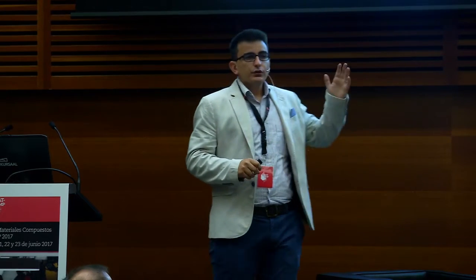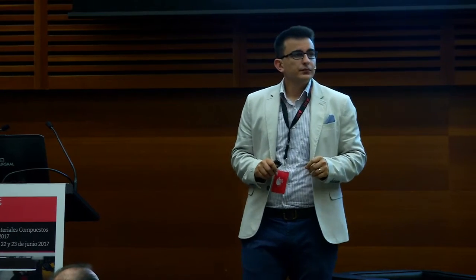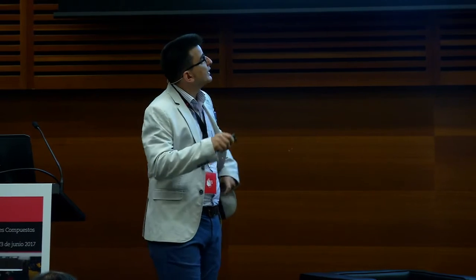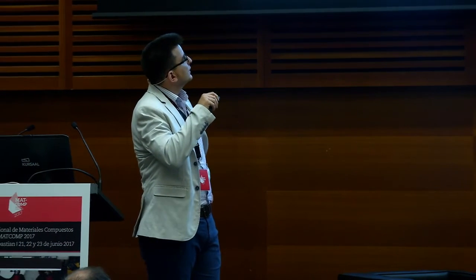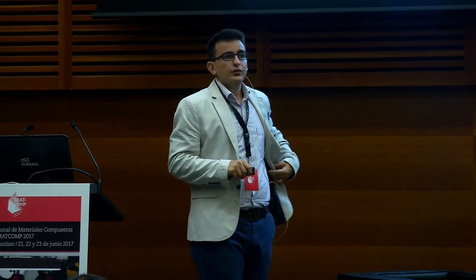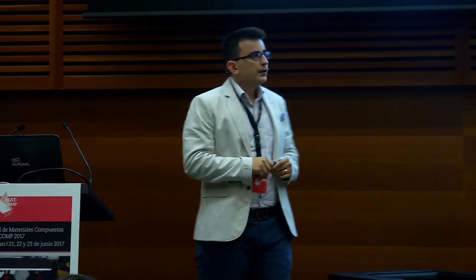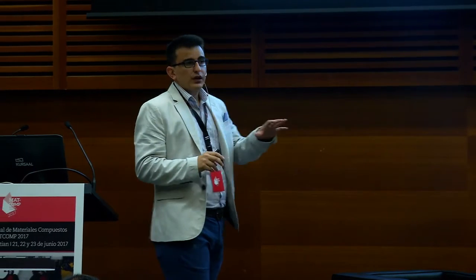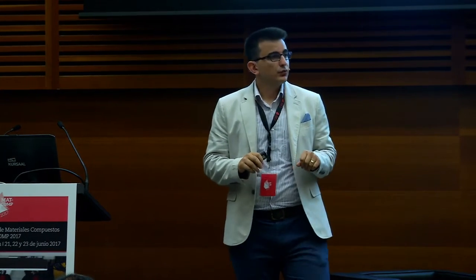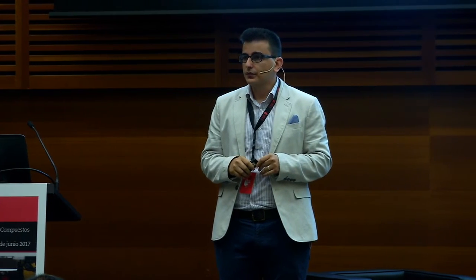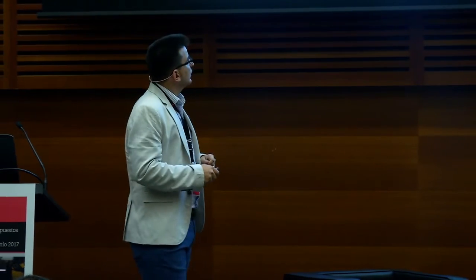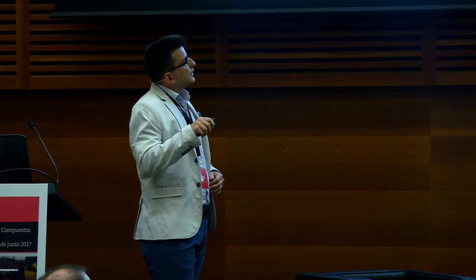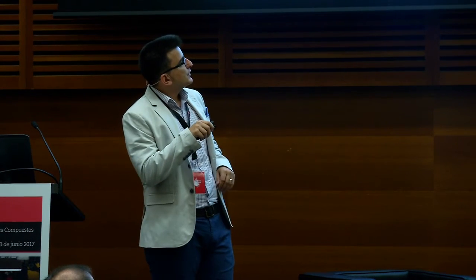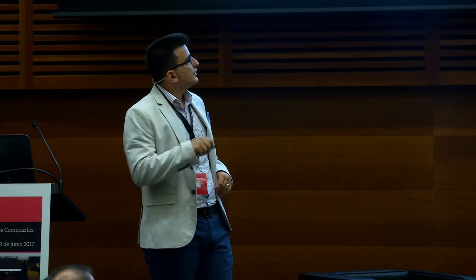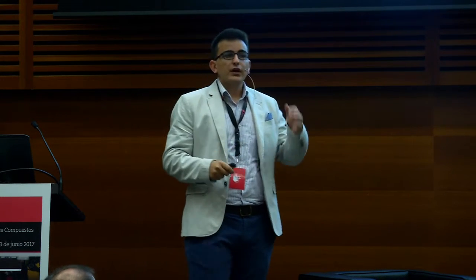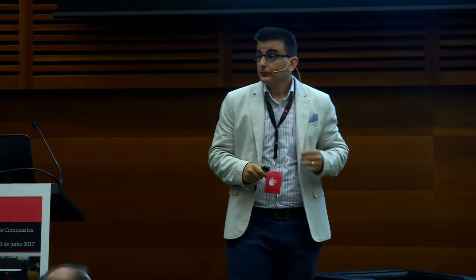So now we know the local fiber volume distribution with the local mesh, and now we can embed this mesh into the existing cross-section of the model. In the existing model, we have uniform fiber volume content of 55%. If we add this local mesh here, we have a specific distribution of the fiber volume here, and the remaining region has a uniform fiber volume of 55% again.